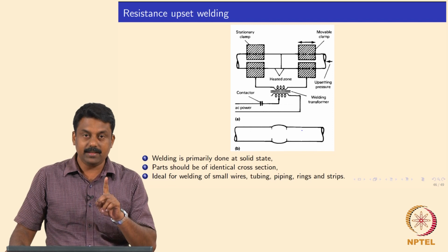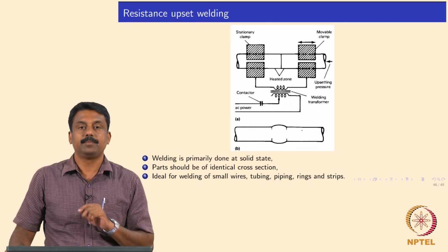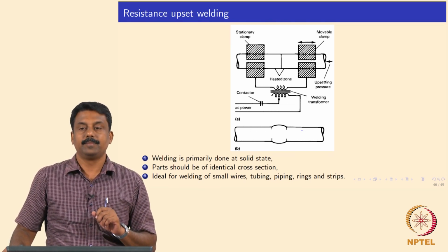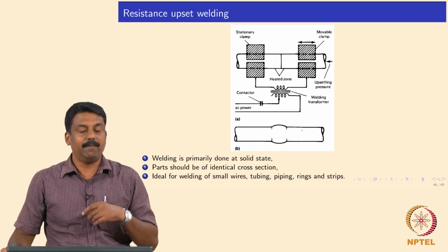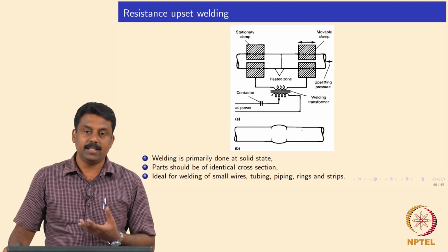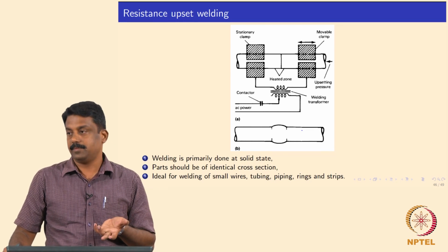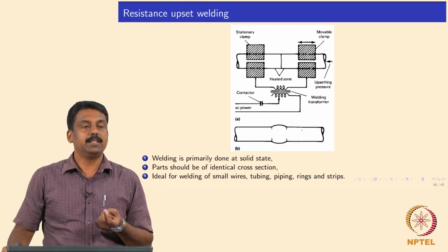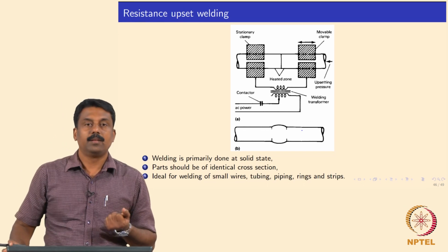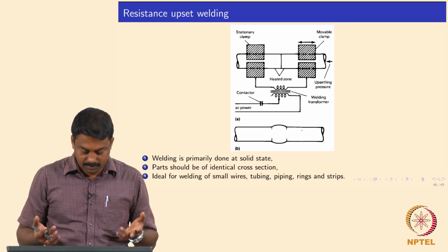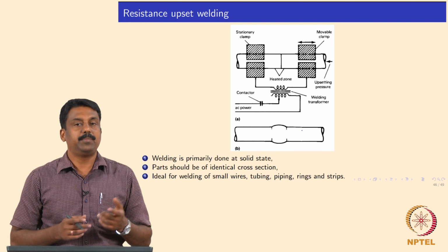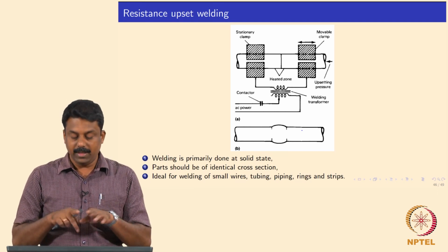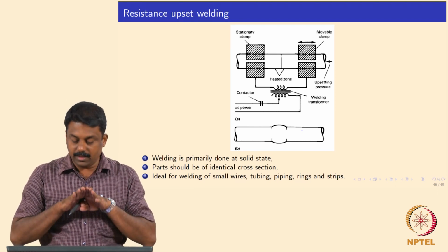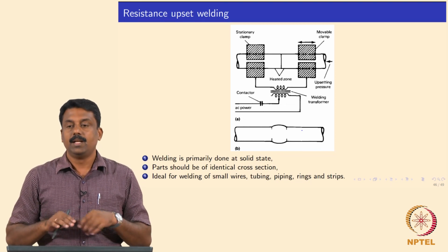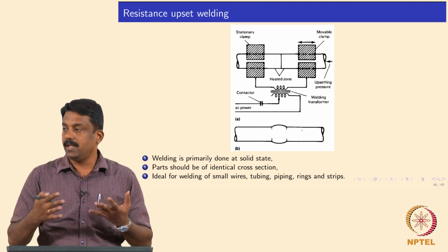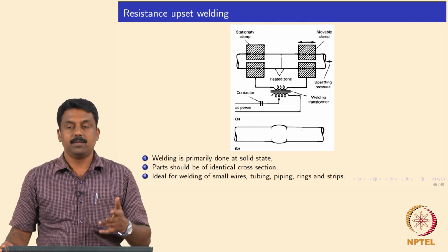Because of that, the interface has to be prepared very well. Otherwise, if you have an oxide, or some contaminants or grease, they would be trapped inside the weld. It is clear. Resistance upset welding is also very commonly used for wires, pipes and tubes, where you keep the interfaces together and then apply an upsetting force, so that you get a mechanical deformation at the interface leading to a joint formation.